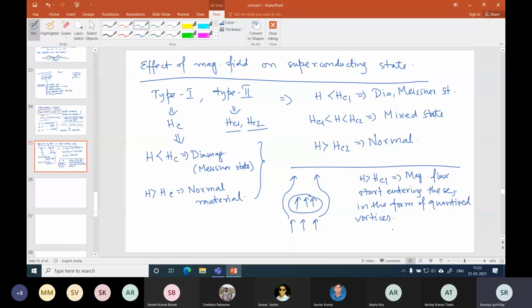When I say quantized vortices, that means it will be like a single quantum of flux which has a particular magnetic field, I think some 2.07 times 10 to the minus 15 Weber, something like that. That much magnetic field will be contained in one of these fluxes, and they will slowly start entering the material. If the field is a little higher than Hc1, then one unit will enter, then a second one will enter, and depending on the value of the magnetic field, a large number of these vortices will enter.